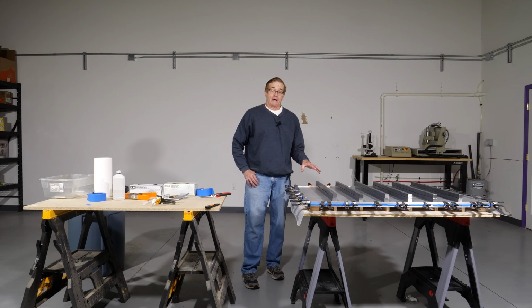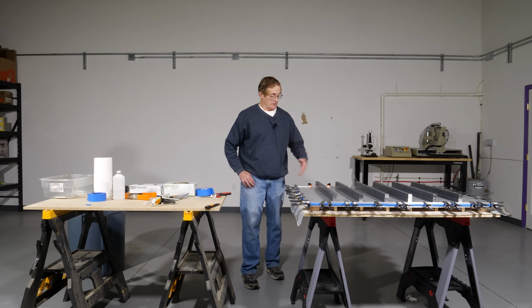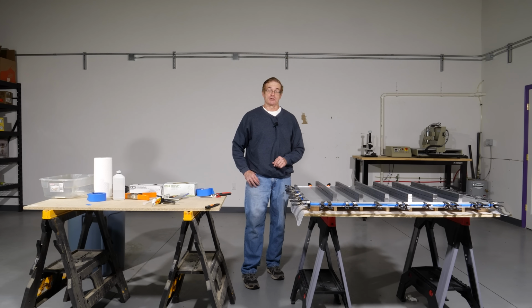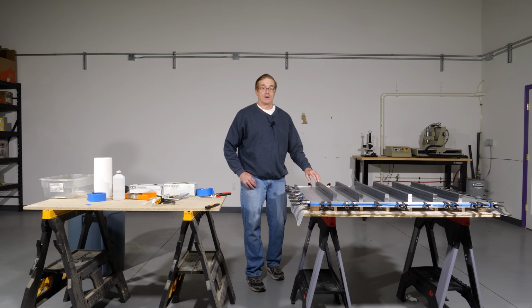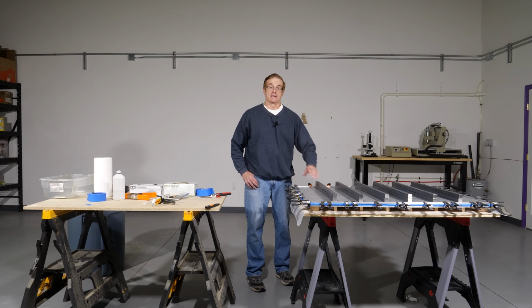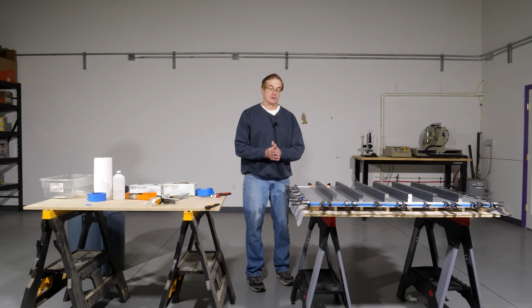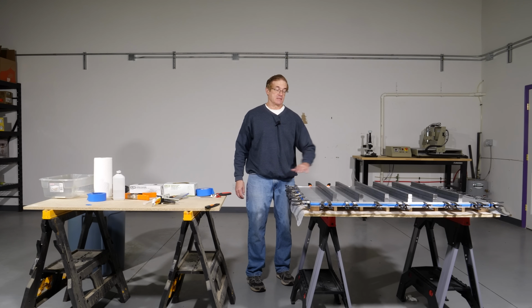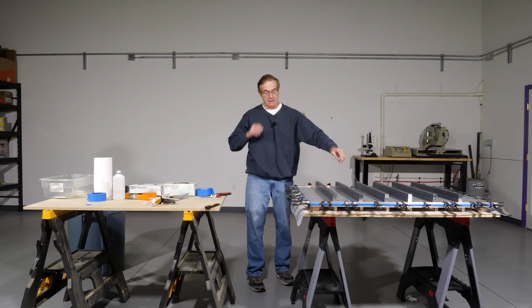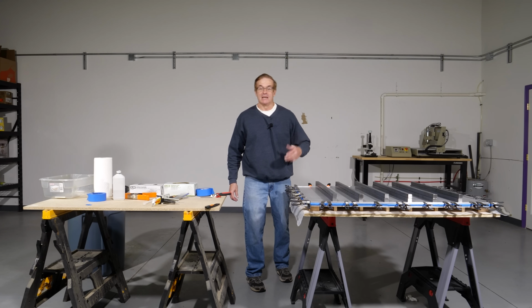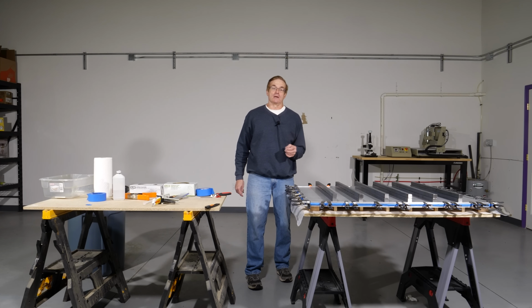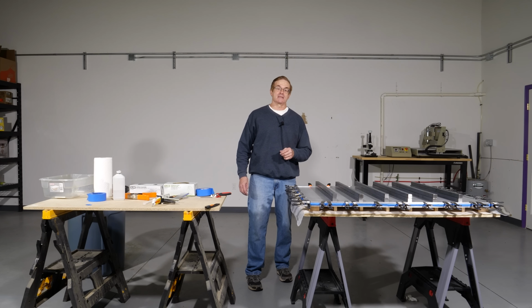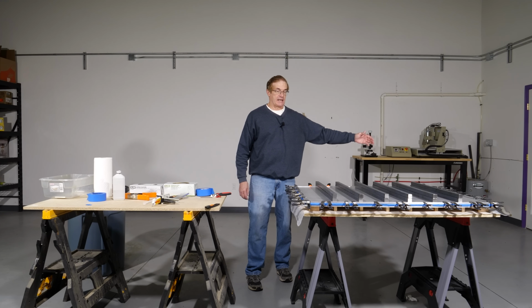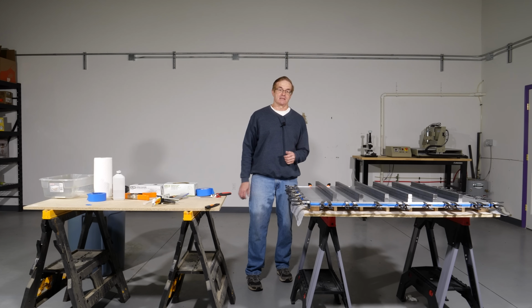All right, took us about an hour, and the old adage, you can never be too rich, too thin, or have too many clamps. These iron rods on top are just compressing the glue on the ribs to make sure that we get good adhesion between the ribs and the surface sheets. And the tape that was placed around the edge is simply to retain any of the extruded epoxy so that we didn't end up covering our clamps and the floor with a bunch of epoxy that drips out.